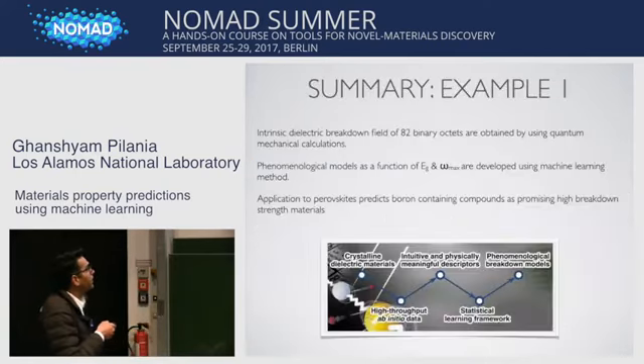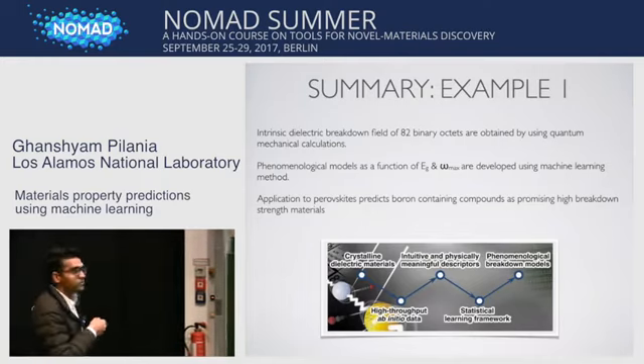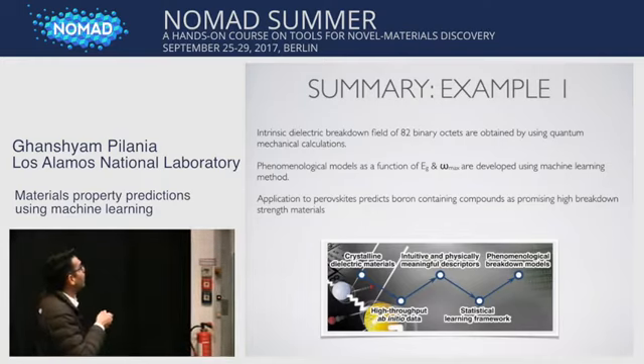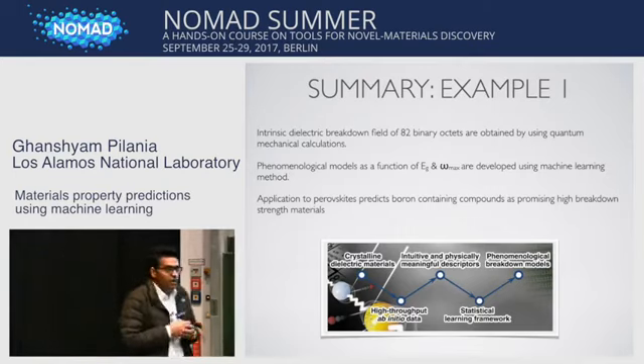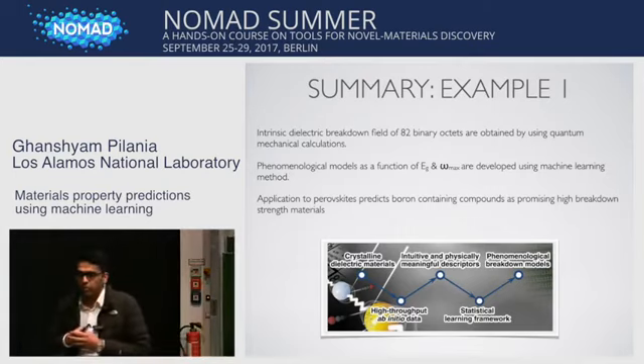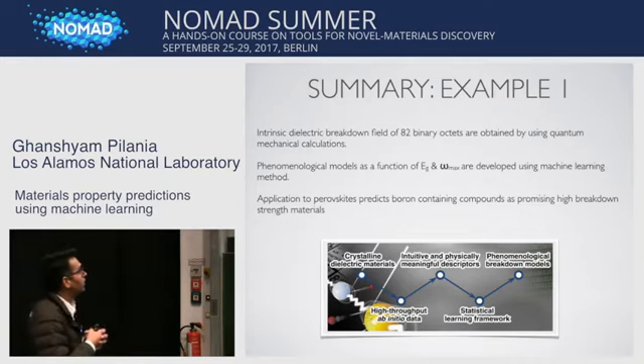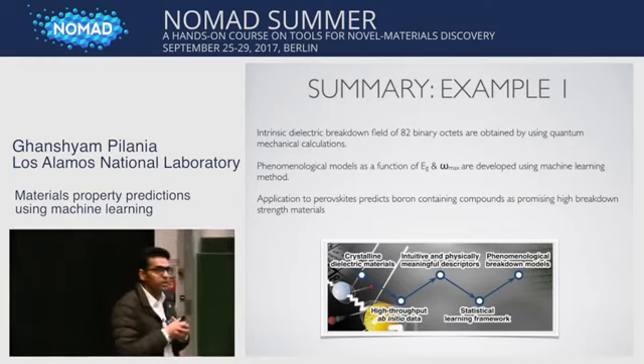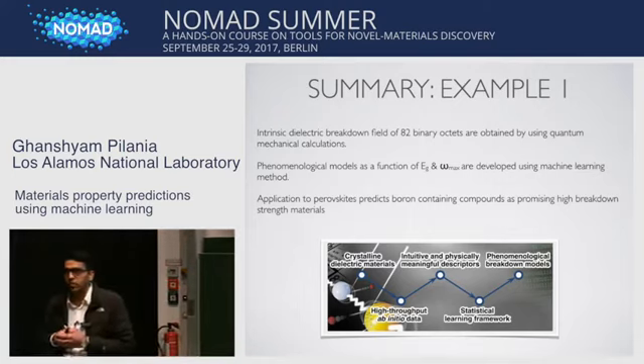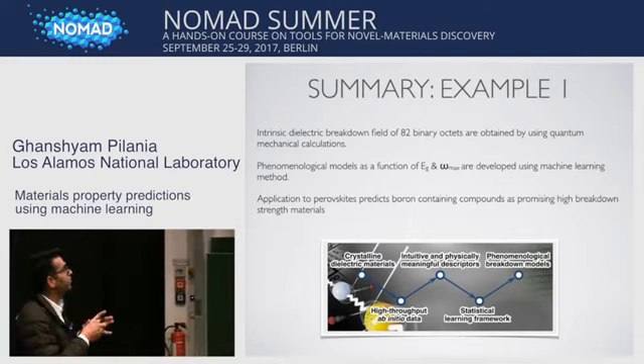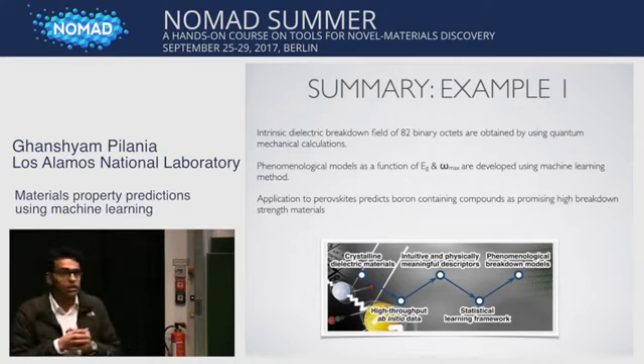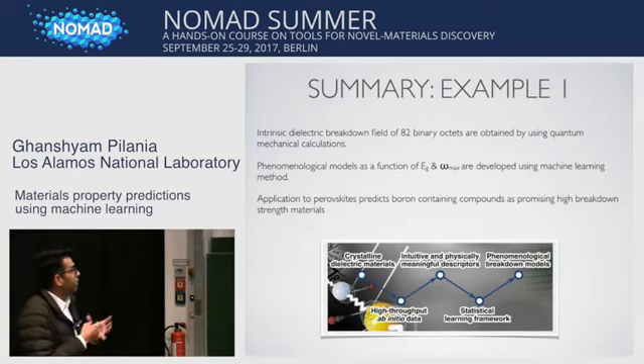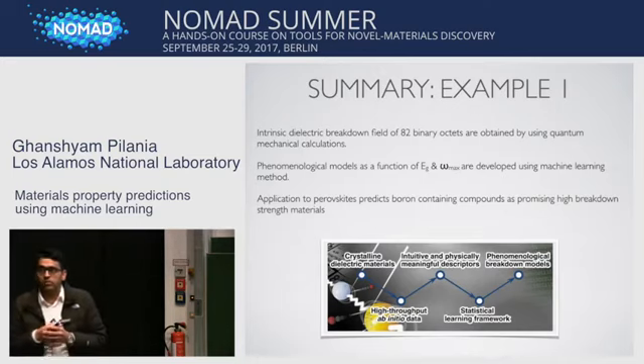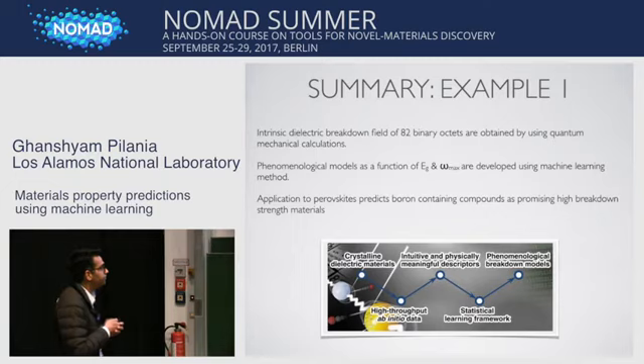So this brings me to the end of this first example, and summarizing, I showed you that we have used a first principles based framework to compute breakdown field strength for 82 binary octets, and then we use this data to train a machine learning model that then allows us to compute breakdown field strength just using two simple attributes like band gap and phonon cutoff frequency. Then we use this machine learning model on perovskites to screen a large compound space, and at the end of the day we find that boron containing compounds seem to be promising for high breakdown field strength applications.